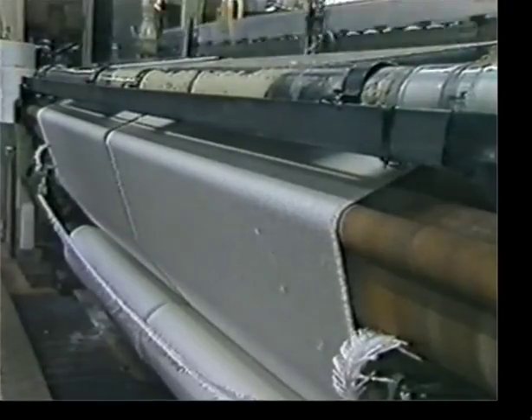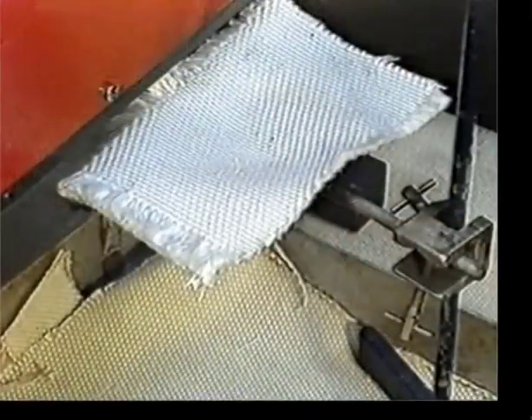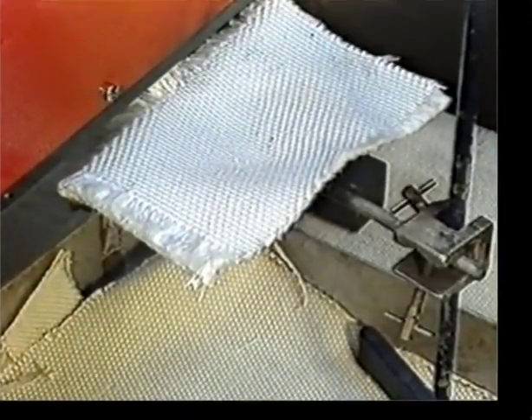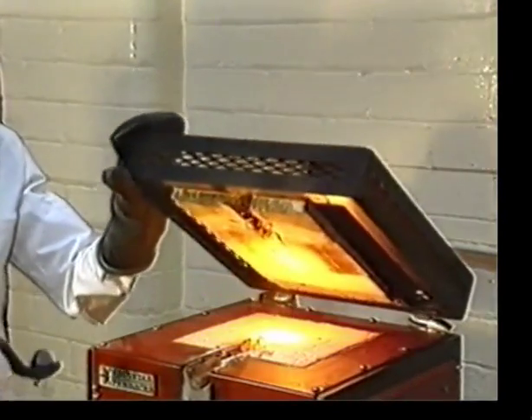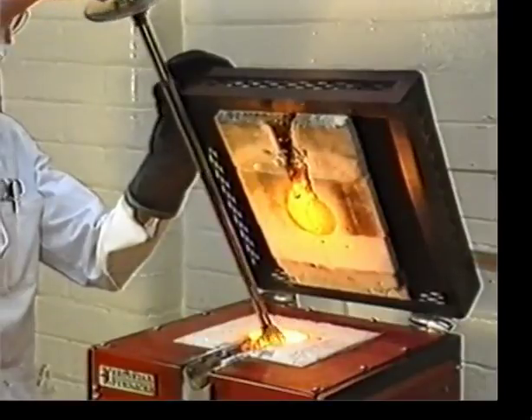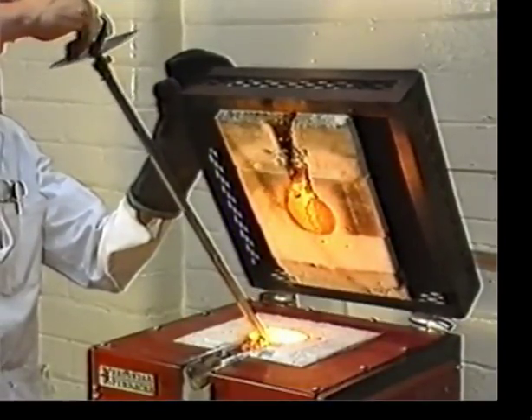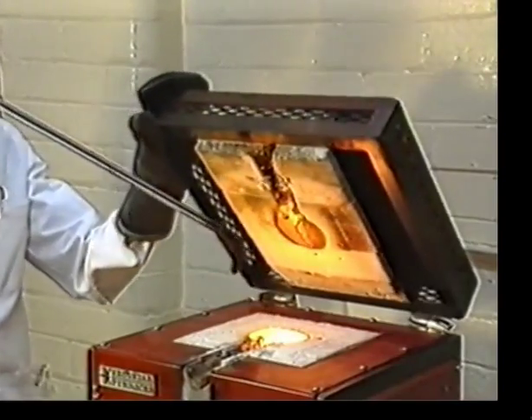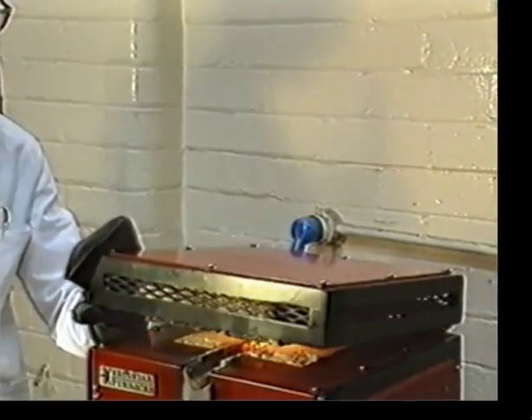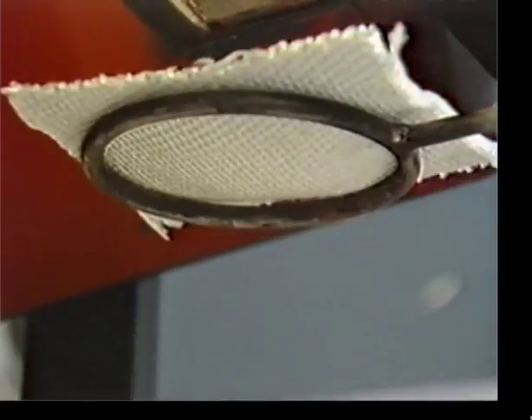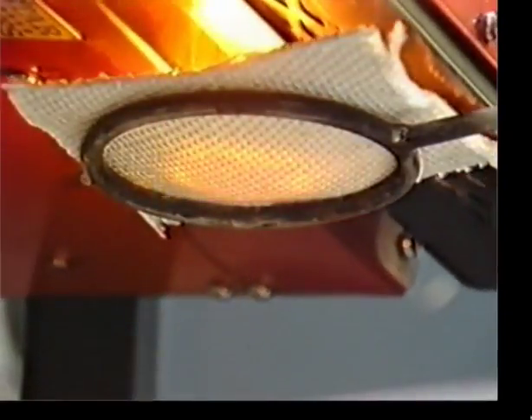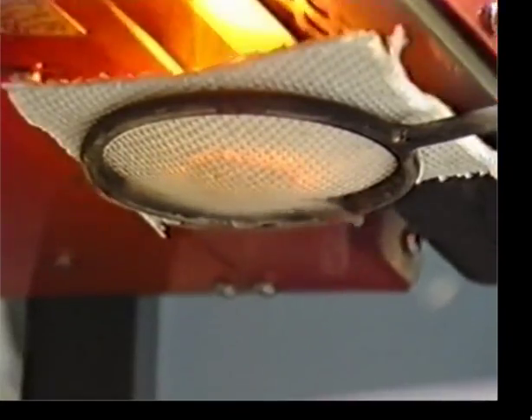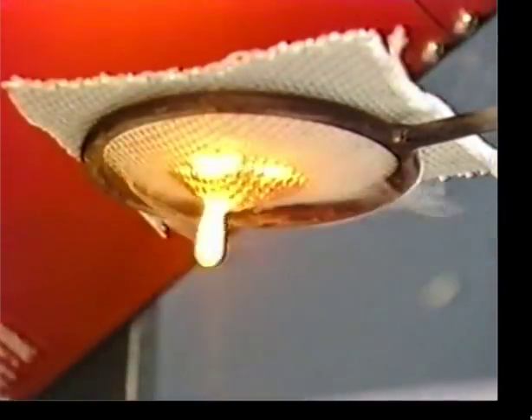During the next few minutes, we'll show you how Weldstop copes with extremely high and sudden temperature surges. In the first test, an untreated glass cloth undergoes a dramatic and searching examination of its insulation properties. A furnace prepares a sample of molten cast iron at over 1,450 degrees Celsius. 85 grams of the metal are poured directly into a saucer formed from the untreated glass cloth. Not surprisingly, it ruptures within a few seconds.